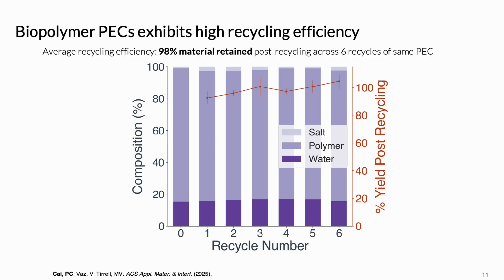A concern I had with the dissolution recycling method was the amount of material lost to the solution during each recycle. So I measured the mass before putting the material in salt water to dissolve, and after it had been formed into a new piece of plastic. On average, over 6 recycles of the same material, 98% of the initial mass that was dissolved was retained by the recycling process, and the composition of the plastic was consistent throughout, with around 3 to 5% salt, 15 to 20% water, and the remaining 75 to 80% polymer.